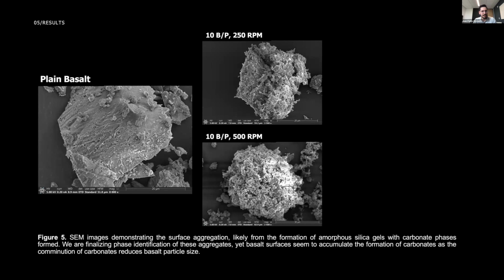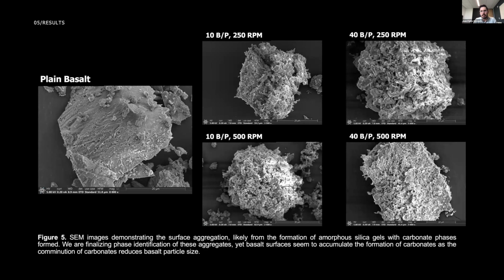We have really interesting hypotheses for why this is happening. We have indications to believe that this is amorphous silica gel clustered with carbonates, and they are why we have not only the carbonates that we see in the TGA, but also that increased reactivity. Now, when we look at 40 ball to powder ratio, this is our highest reactivity SEM that we can produce from basalt. Yes, we're decreasing the particle size of basalt, but we can see that you still have those clusters forming, with large disruptions to the surface morphology of that particle.